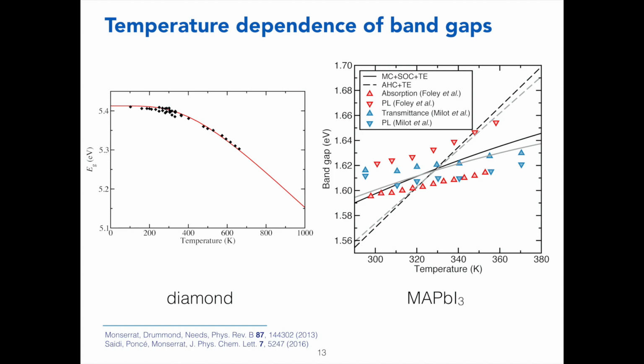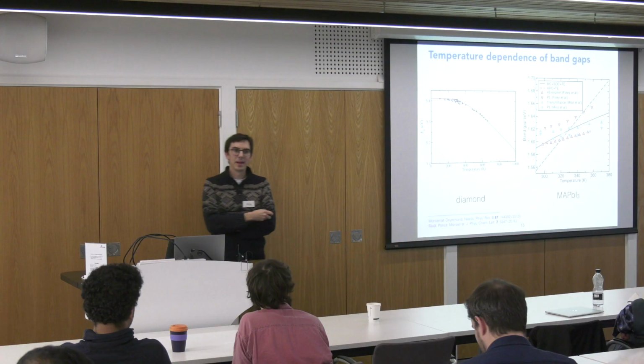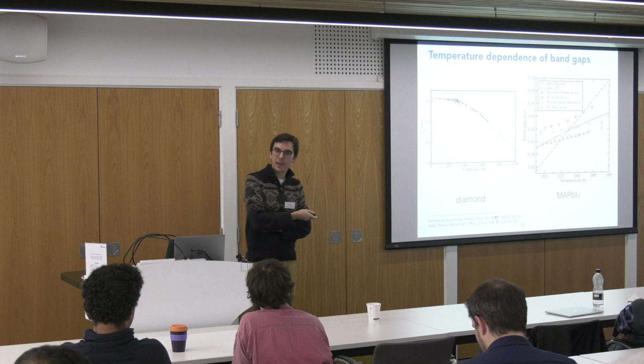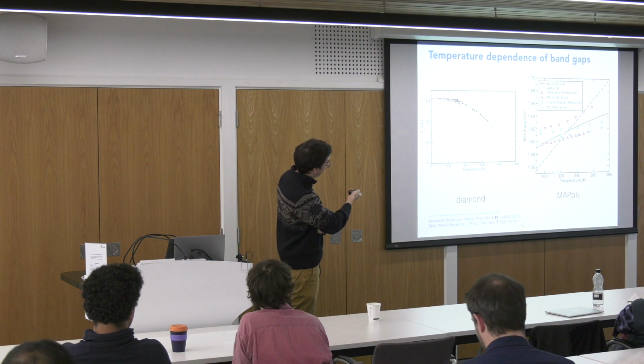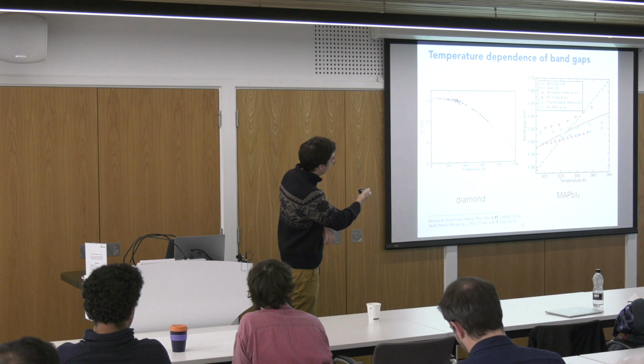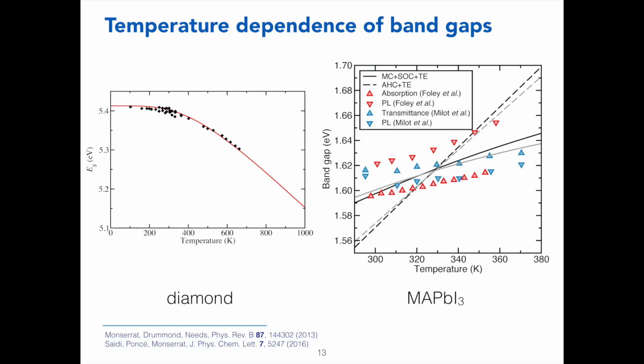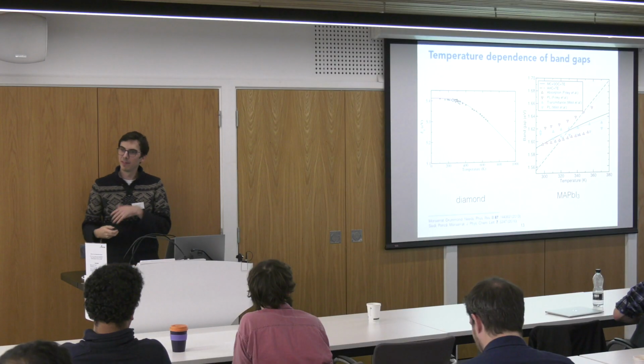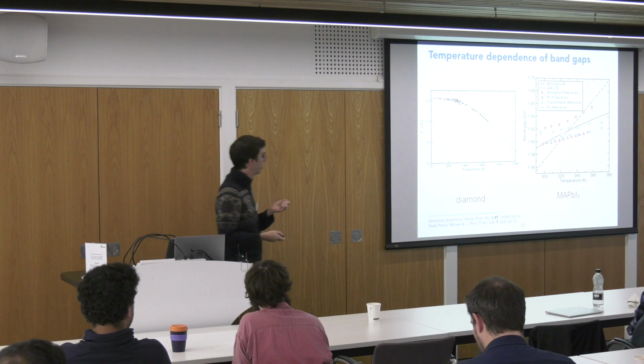And what's interesting is that at high temperatures, we have this linear temperature dependence. And in a sense, that's the classical behavior of the temperature dependence, which is only determined by the Bose occupation factor of your phonons. And then at low temperature, we have this sort of saturation of the band gap. And that's a purely quantum effect. So if we only had classical physics, this linear dependence would go on and then cross this band somewhere here. And the difference between that and the real result is the quantum correction to this, which in a system like diamond, which is relatively light, is actually quite large. It's about half an electron volt.